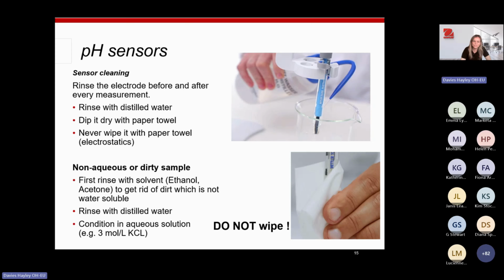For non-aqueous or dirty samples, first you can use a solvent, so you can use acetone or ethanol to get rid of any dirt which isn't soluble in water. But once you do that, you should immediately rinse the solvent off with distilled water, and then you must pop it back into an aqueous solution. So condition it in your 3 molar KCl, or pop it back in your storage solution, just to make sure that any dryness that's occurred from the solvent is rectified in the solution. And again, do not wipe the probe, just dab it dry with your towel.